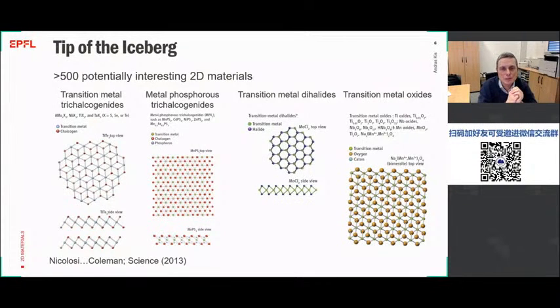So you can start off with, for example, a 2D semiconductor that has a certain band gap, and then by changing the thickness, you change very easily the band gap. Or you can easily induce doping or magnetism by replacing atoms or chemically functionalizing the surface. All these 2D materials can also be strained to very large amounts of strain. That is another tuning knob that you can use to modulate the properties. And of course, you can also use magnetic fields, electric fields, and gating. Since 2D materials are pretty much composed of surface atoms, they're much, much more responsive to this kind of tuning.